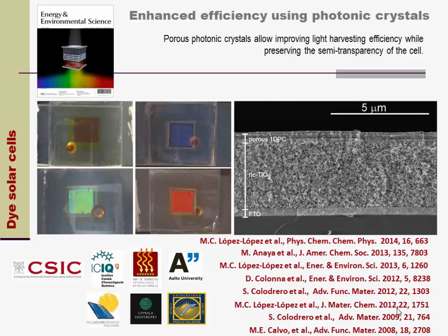You have to think that with these mirrors we can get 78% reflected, while to get that reflectance with the diffuse scattering layers, we need something like 4 microns of our nanocrystalline electrodes. So we get the same reflectance with just maybe half a micron. So we demonstrate that we improve efficiency. Actually, you can also provide the device with color. So you get two things, right? You get efficiency enhancement and controllable color.